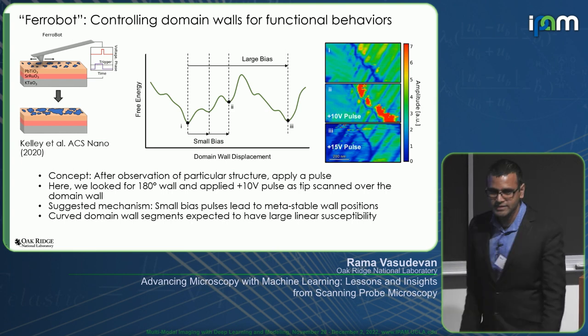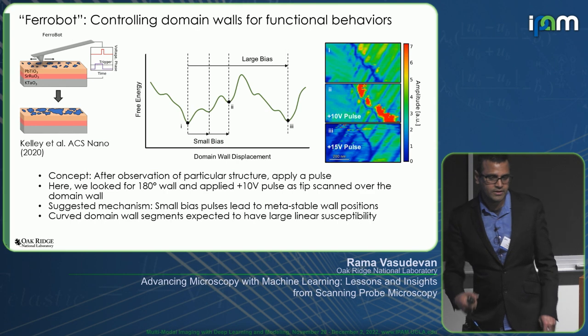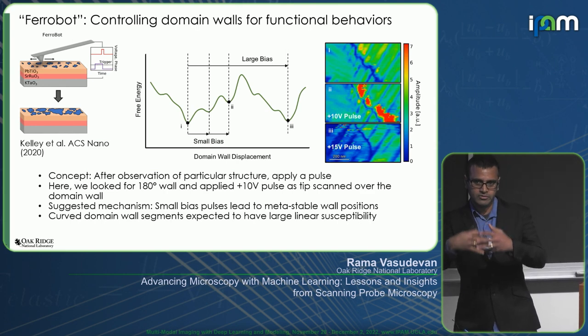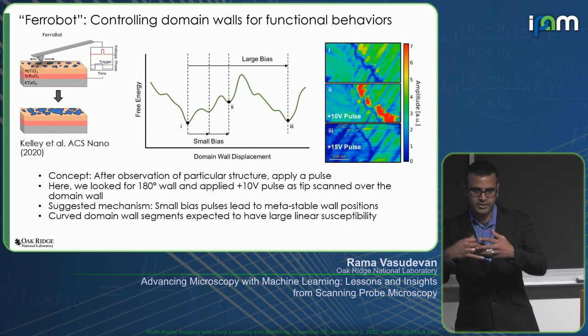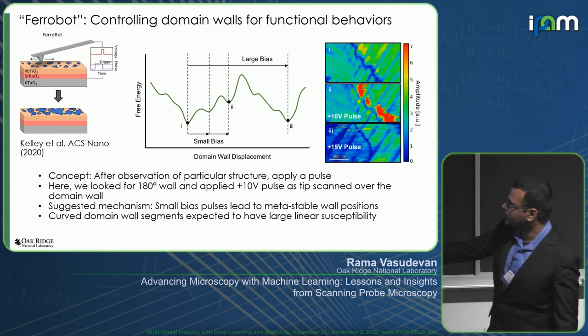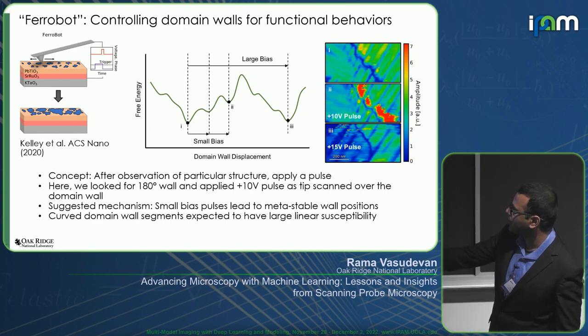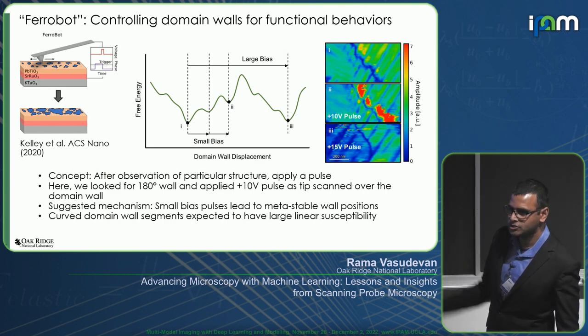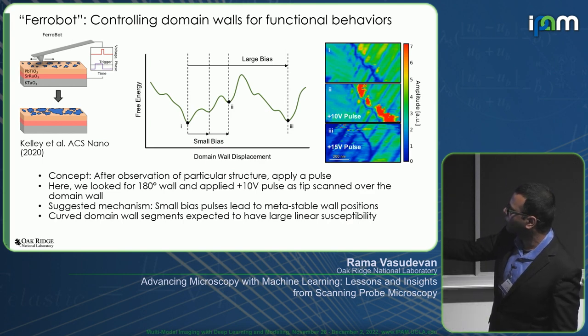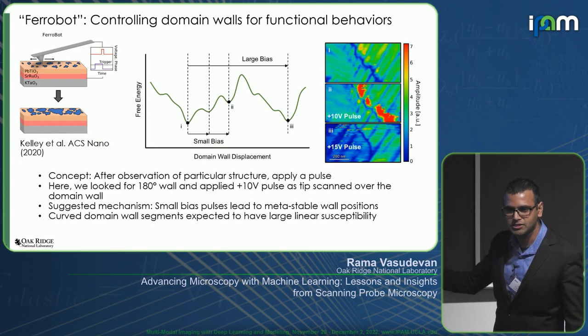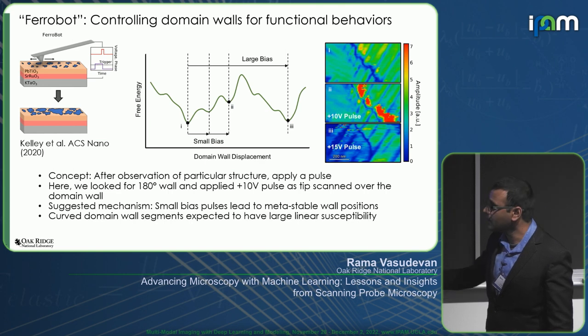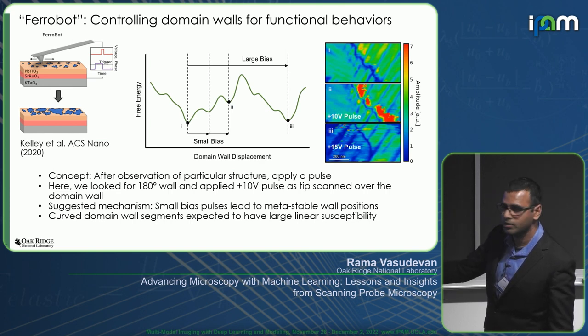after this particular experiment. So why is that happening? The reason is that every time you apply a voltage pulse, you are moving the wall to a frustrated configuration, which is a high energy configuration for the domain wall, and this leads to higher susceptibility. If you do the calculations, it will give you more electromechanical response. And so we've basically engineered a metastable state in our ferroelectric material, which has higher response, through nothing more than a very simple automated system.